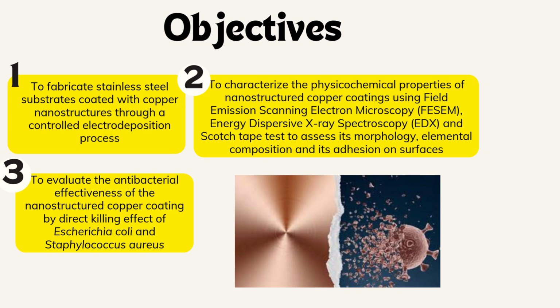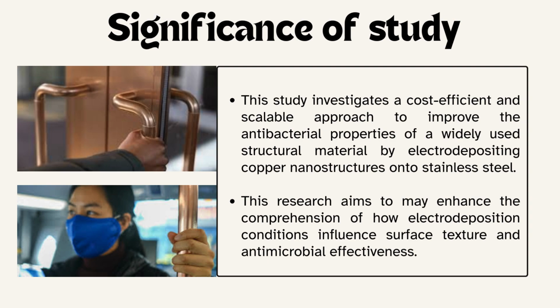Moving on, the objectives of the study are, firstly, to fabricate stainless steel substrates coated with copper nanostructures through a controlled electrodeposition process. Secondly, to characterize the physico-chemical properties of nanostructured copper coatings by using FESEM, EDX, and Scotch tape tests to assess its morphology, elemental composition, and its adhesion on surfaces. And lastly, to evaluate the antibacterial effectiveness of the nanostructured copper coating by direct killing effect of Escherichia coli and Staphylococcus aureus.